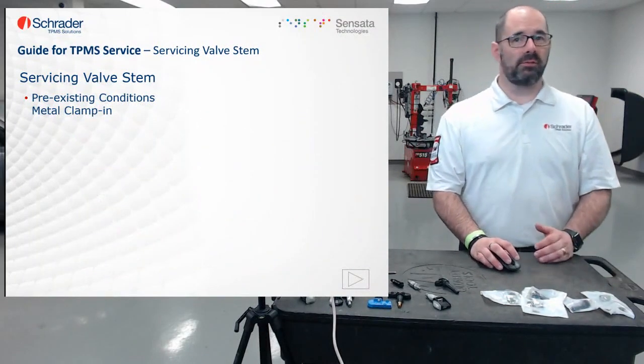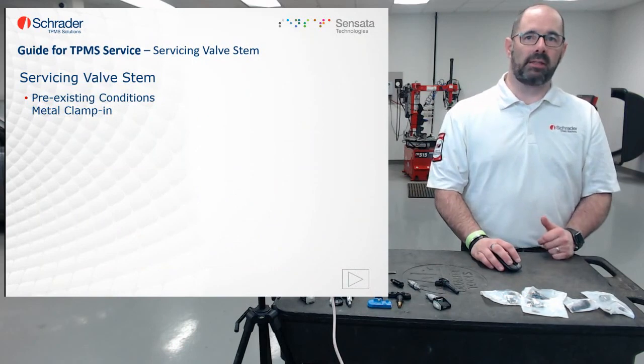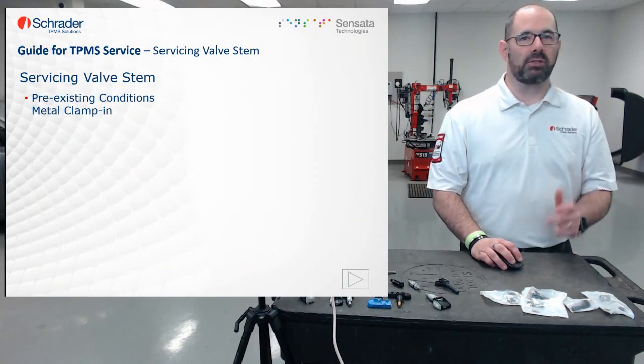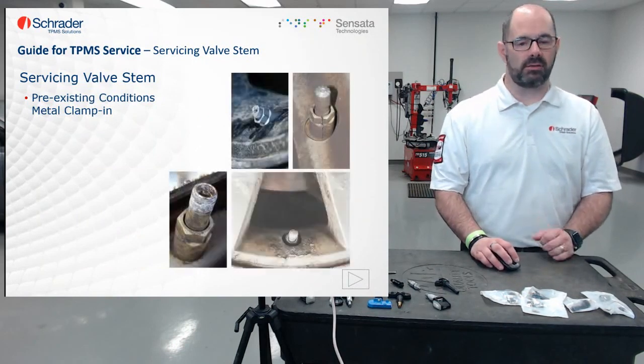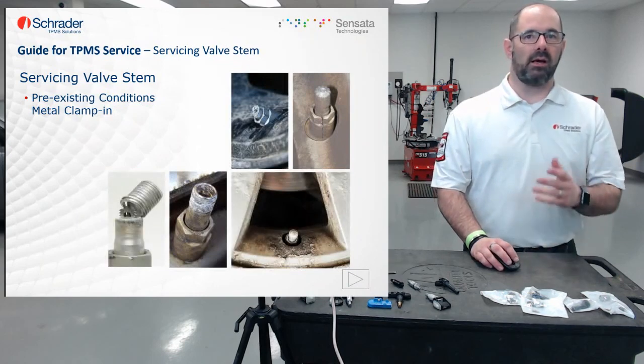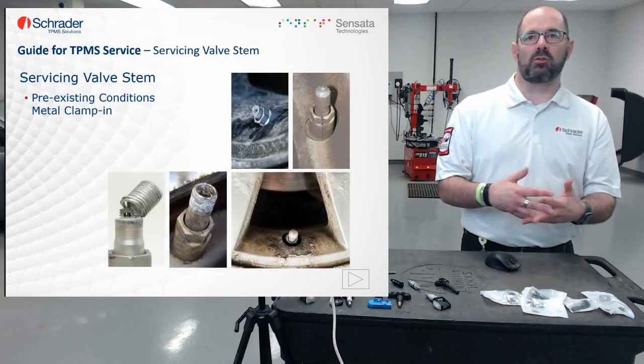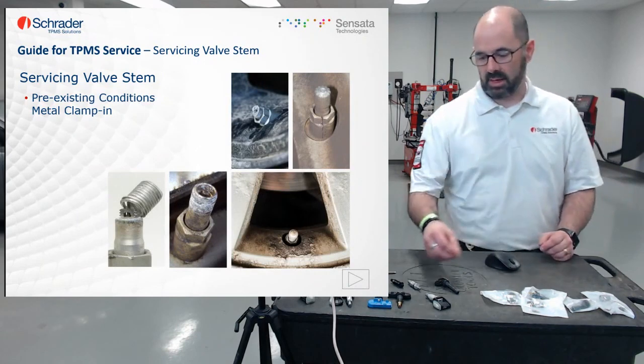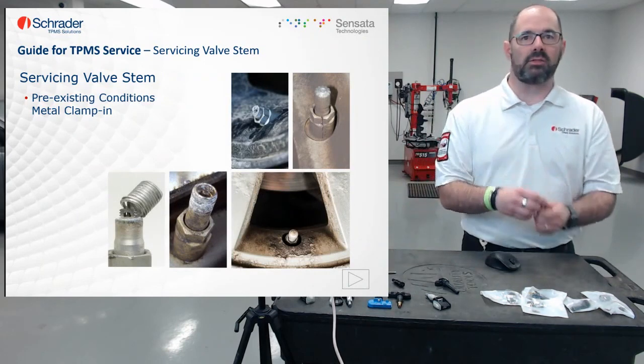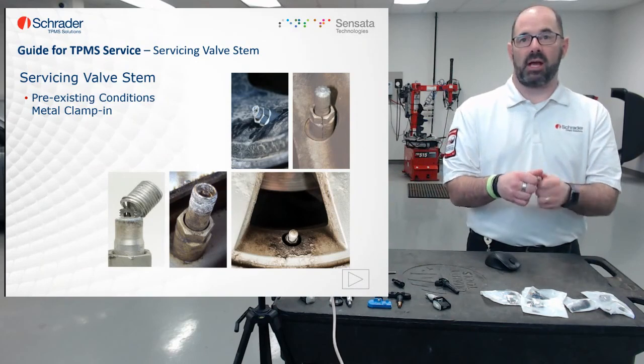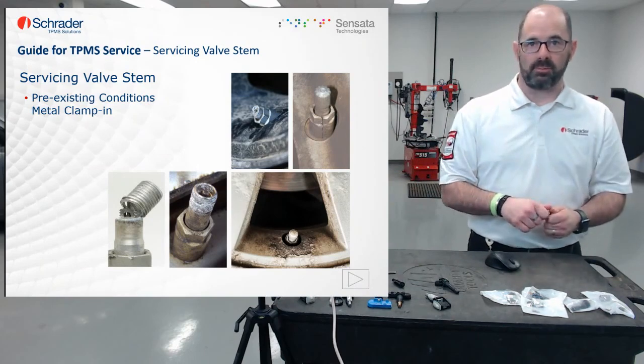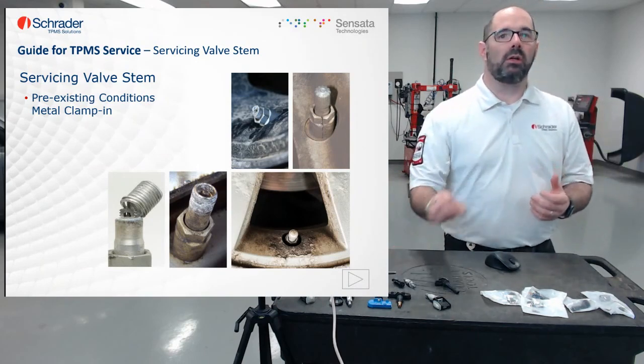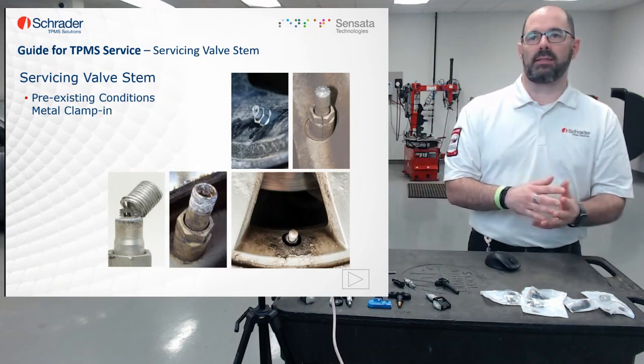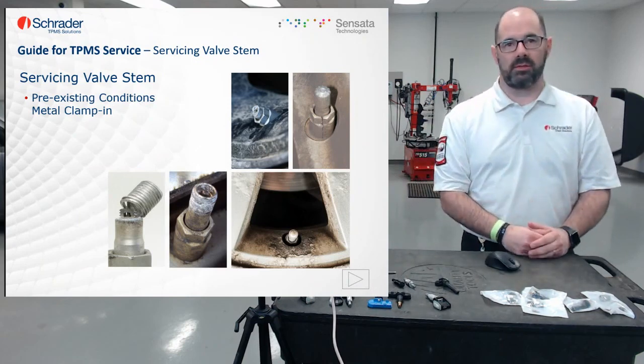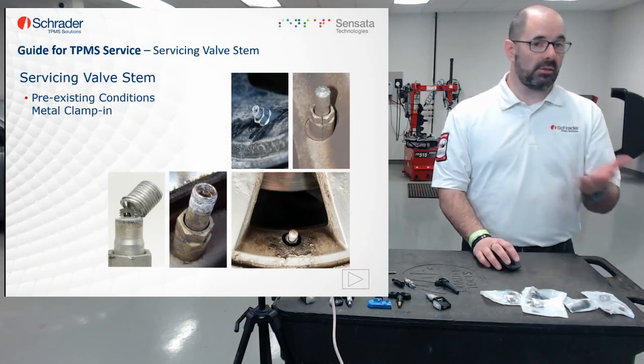Same goes for the aluminum valve, the metal clamp-in stems. Unfortunately, we see too many of these corroded valve stems. The aluminum valve stem can corrode to a point where the components and sides are seized and bonded together. Sometimes it can even be a challenge just to remove them from the rim. It's very important to identify any pre-existing damage before you start servicing the vehicle, because if you break it, well, you're stuck with the problem now.